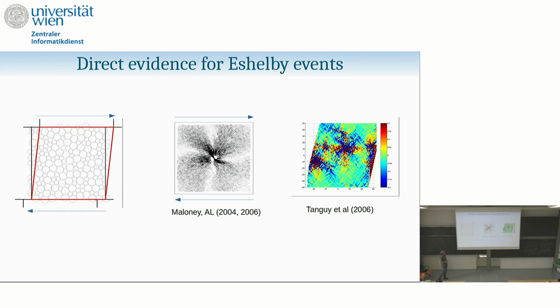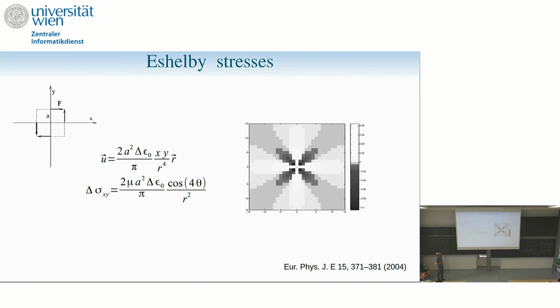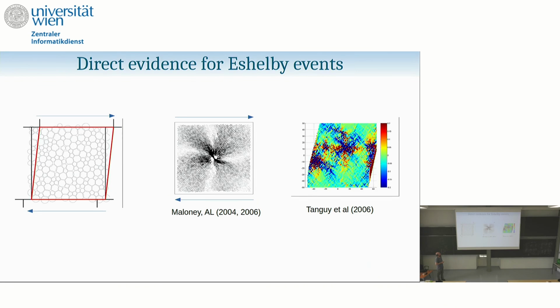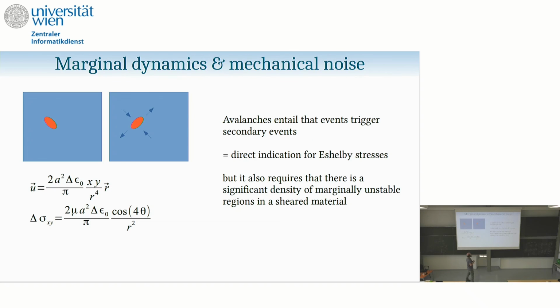So the idea is, you take a system, for example, I showed you this eigenmode, this mode leading to instabilities, and it's really the expected displacement field. You can take a cut through these lobes and you find the expected radial dependence. This is from another paper, where people looked at the stress change, and you can find here this signature of a quadrupole. You have these lobes here, though it's a bit hard to see in the diagonal. So we see Eshelby events in the plastic response.